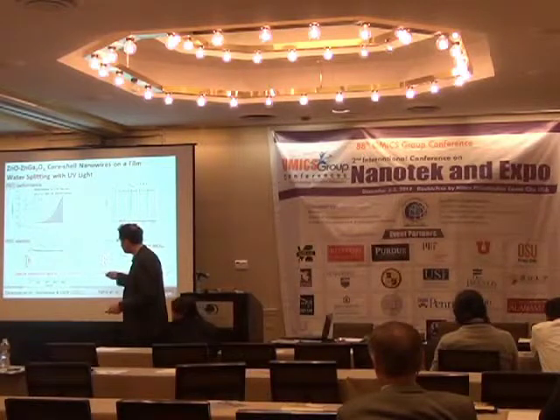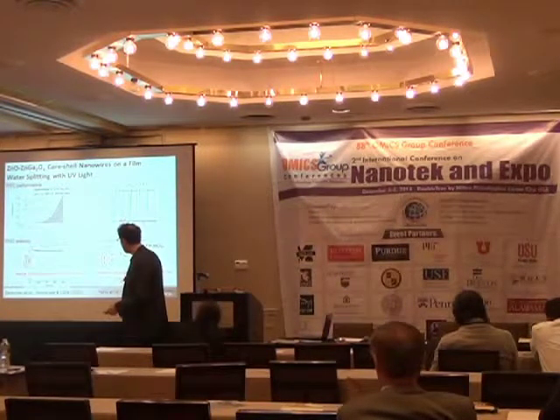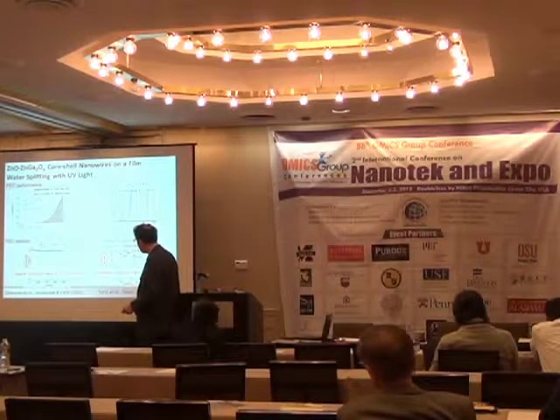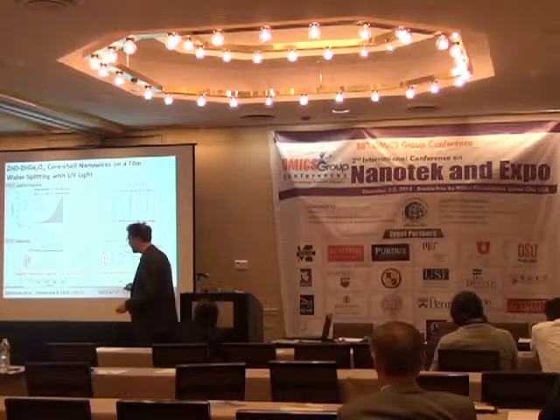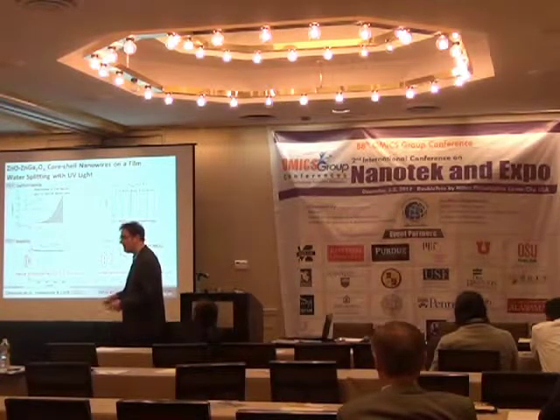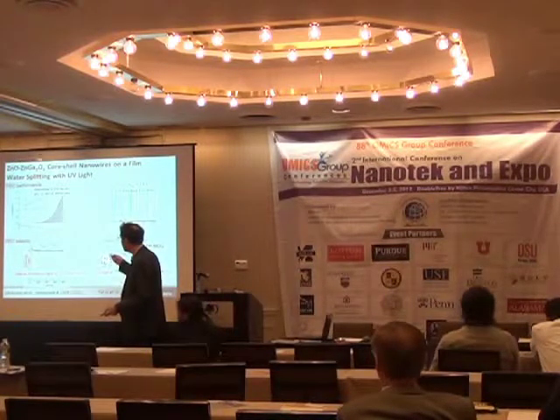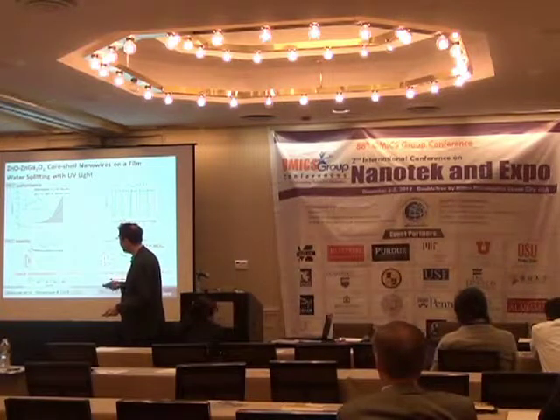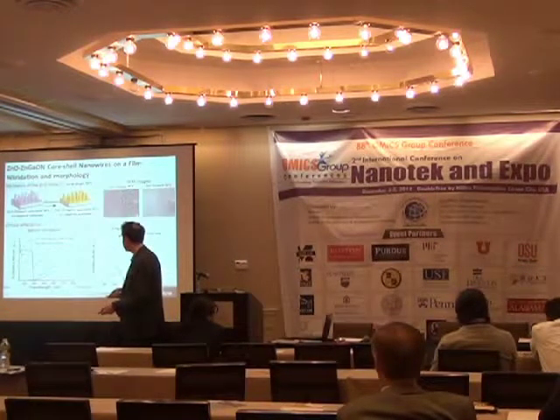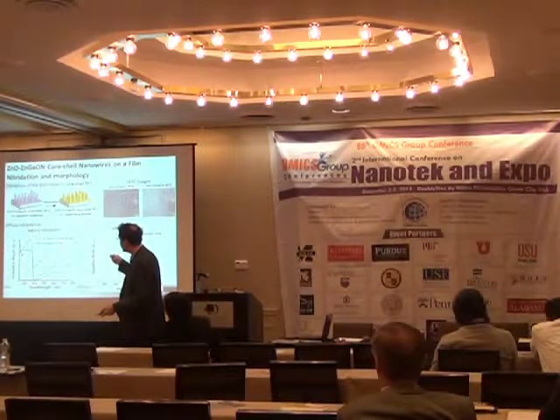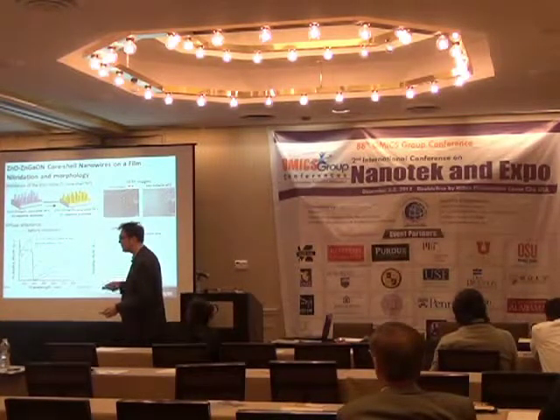So what is important is the stability of the process in time. You see that it's pretty stable, so the current is stable in time, and you can compare that with results published on zinc oxide nanowires, where you see a quite strong decrease in the current as a function of time, because the zinc oxide is being damaged by the photocatalytic process. So this shell allows us to protect the nanowires. Okay. The final thing that we did was to use a nitridation process to increase the absorption of light.